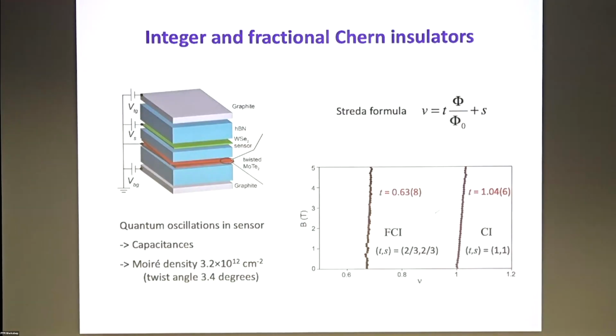So I don't want to get into the details, but we can actually use the quantum oscillations of the sensor to calibrate each of the gate capacitances and calibrate the twist angle. And with that, we can determine the two quantum numbers in the Streda formula, T and S. For the 1 state, T within error bar is equal to 1, and S is also equal to 1. For the 2/3 state, within error bar, T is equal to 2/3, and S is also equal to 2/3. So these measurements show that the 2/3 state is actually a fractional Chern insulator.